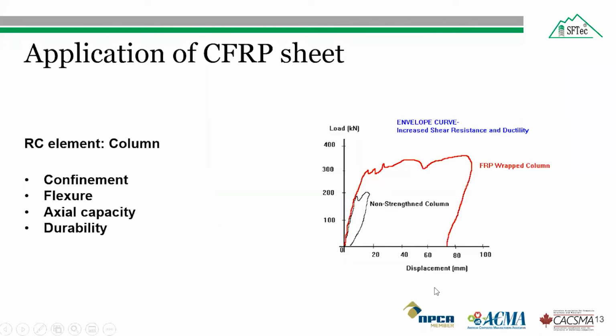And the following load displacement plot shows the comparison of the non-strengthened column with the FRP strengthened column. The envelope curve comparison indicates that the FRP sheet increased both shear resistance as well as ductility of the reinforced concrete column. As we can see, the strength of the non-strengthened column was around 200 kilonewton, and in the case of the FRP wrapped column, it was more than 300 kilonewton.